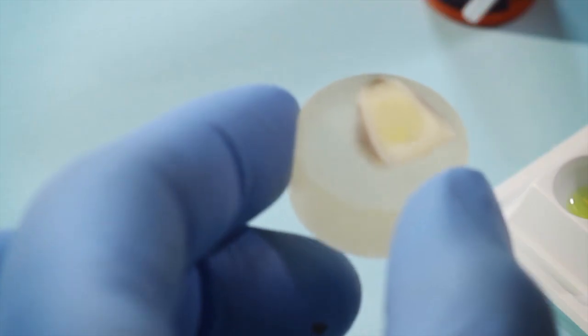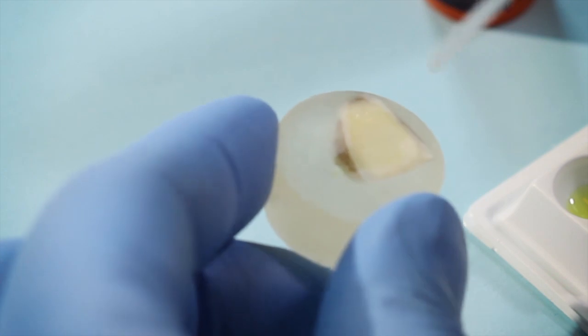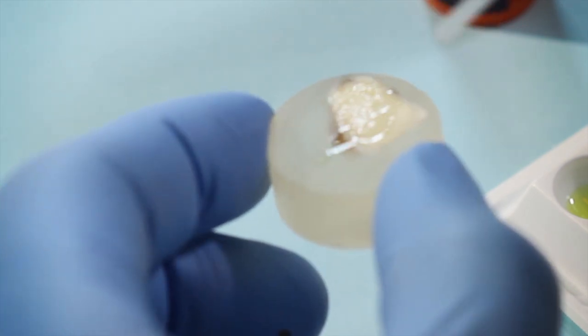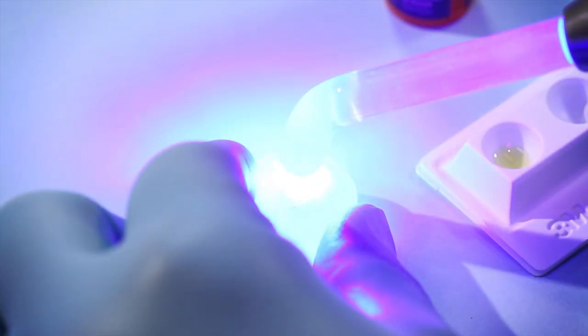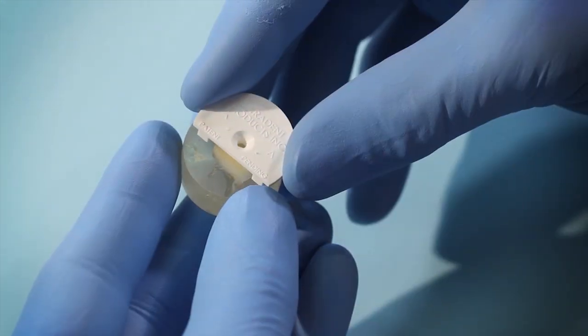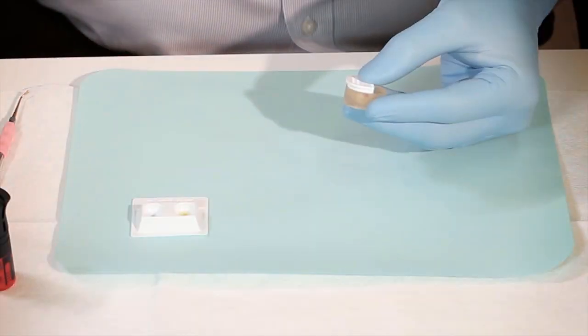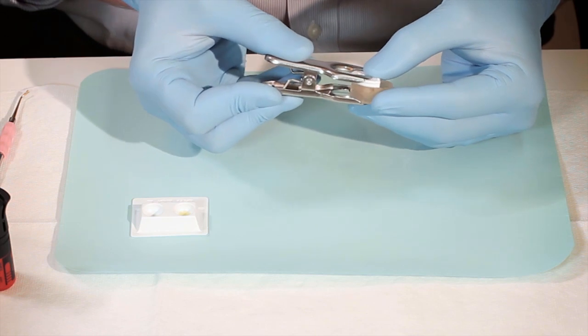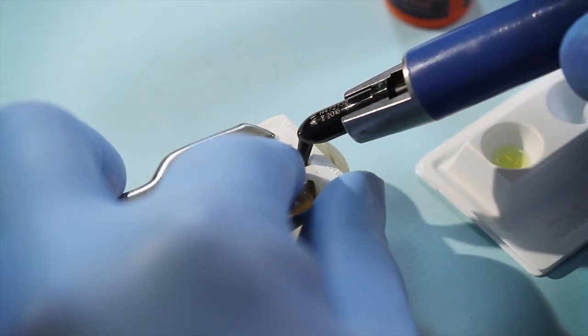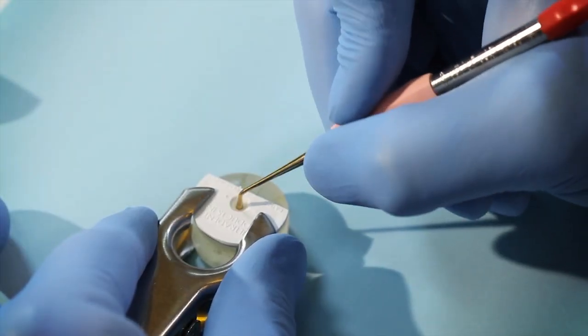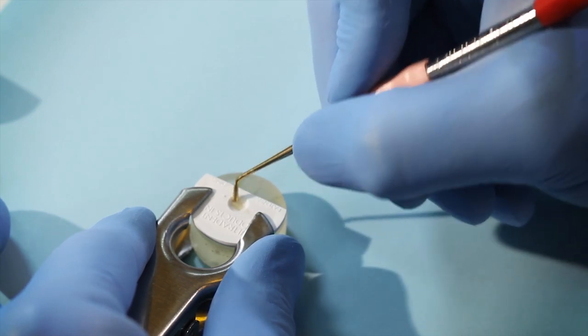It was gently air-dried for 5 seconds to evaporate the solvents and produce a uniform film. Then it was light-cured for 10 seconds. Next, a mold was centrally placed on the cured adhesive and fixed into place with a clamp. A hole in the mold was filled and packed down to create good contact with the adhesive and tooth surface.